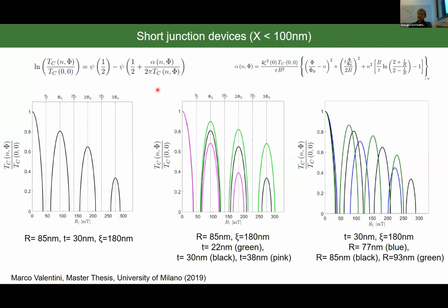Effectively, by using these formulas, now you can plot TC versus magnetic field, and you can really see the Little-Parks effect. But if you would fix the diameter of your nanowire, the radius, the coherence length, and you would change the thickness of your superconductor, you can see that the height of the lobes changes. On the other hand, if you fix the thickness of the superconductor and coherence length and you change the radius, you can shift their position.